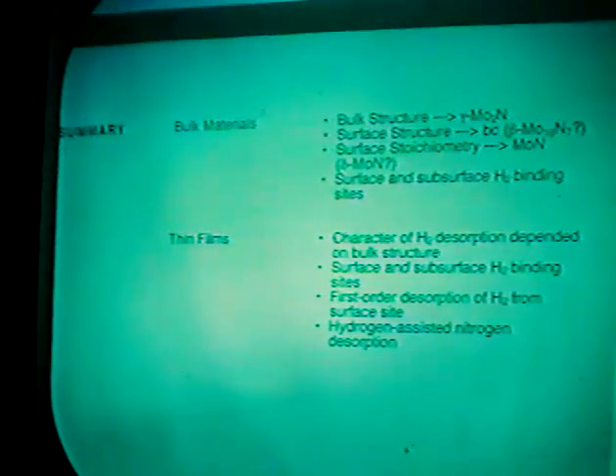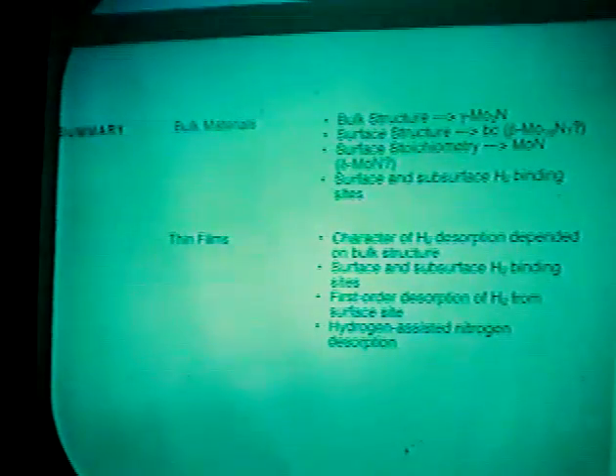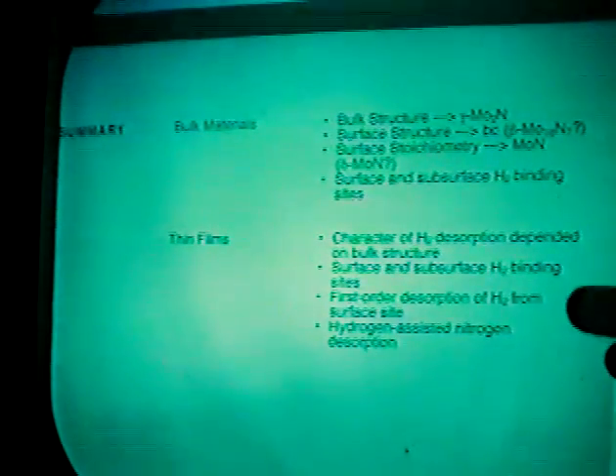Let me just conclude by saying that, as I've gone throughout, this is basically what we see. What's important here is that I think we've identified what makes sample number 8, or this low surface area material, so much different from any of the other samples. You remember that the nitrogen to molybdenum ratio was near 1.